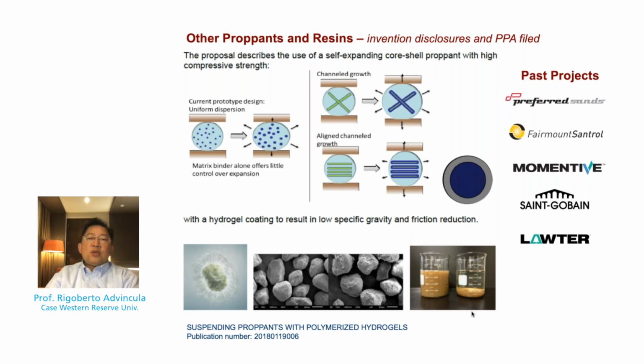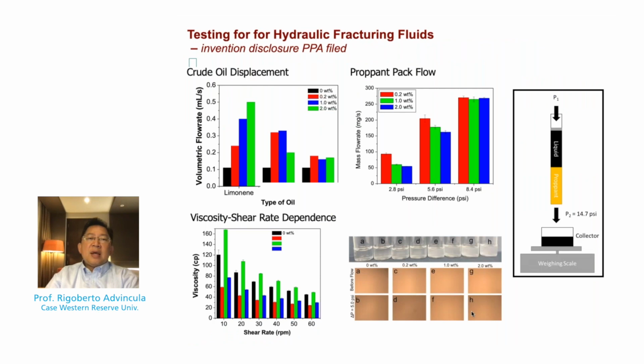So the goal now is to coat these proppants with a hydrogel, for which we have also filed a provisional patent. The hydrogel, together with the high strength of the polybenzoxazine coating, for example, will produce a superior proppant, which combines both low specific gravity and high compressive strength resistance. And then finally, we've done a number of measurements to look at the viscosity, shear rate dependence, proppant pack behavior, and crude oil displacement, even with this type of particles, using unidirectional pressure-driven flow measurements.